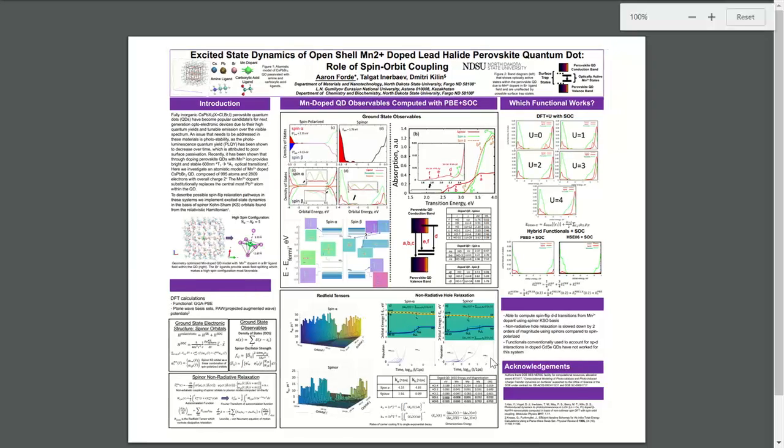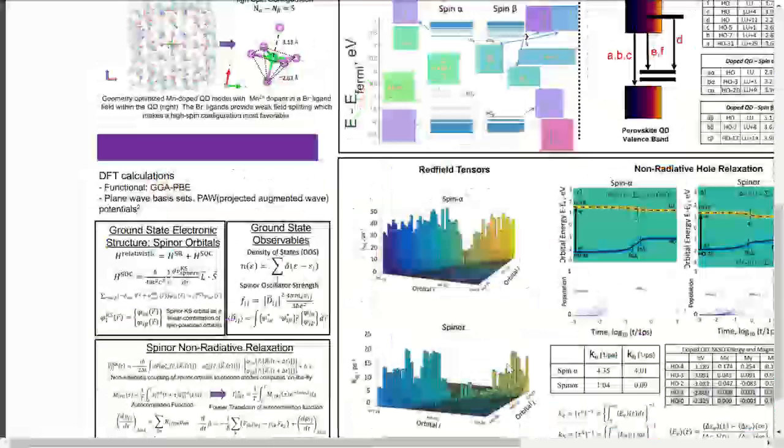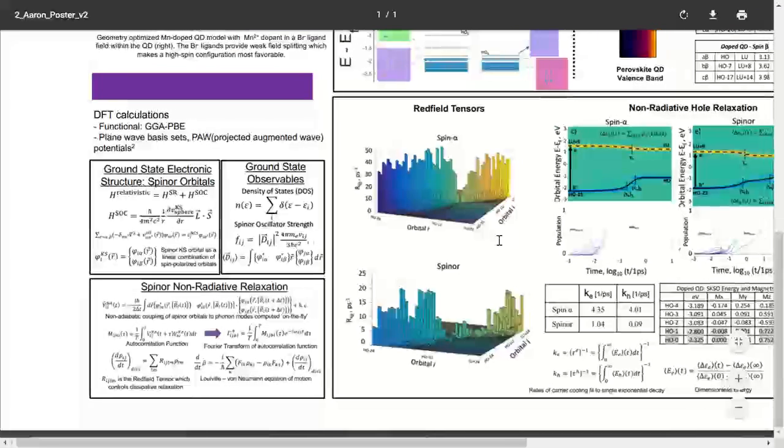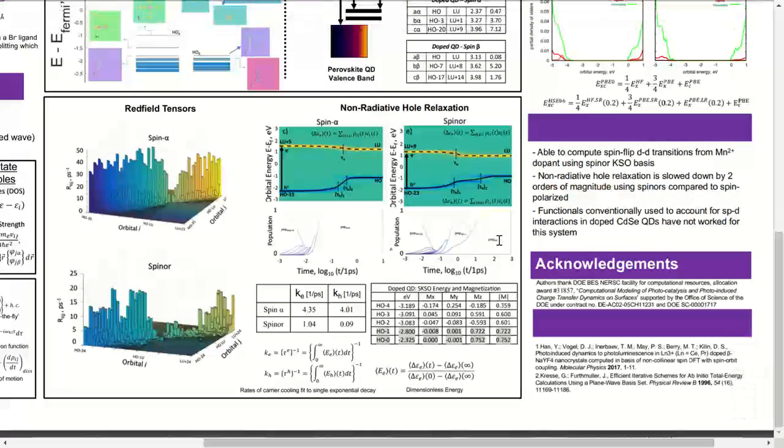More questions? What made you choose those specific relaxations, like your HOMO-15, your LUMO+5? I was trying to see why you chose those specifically. I chose them to get an accurate comparison between the relaxation. So I chose them so that, if this is delta E, that delta E for both of these was about the same. Oh, okay. Because if you assume it follows like an energy gap law, your initial condition will affect that, so you want them to be both the same.